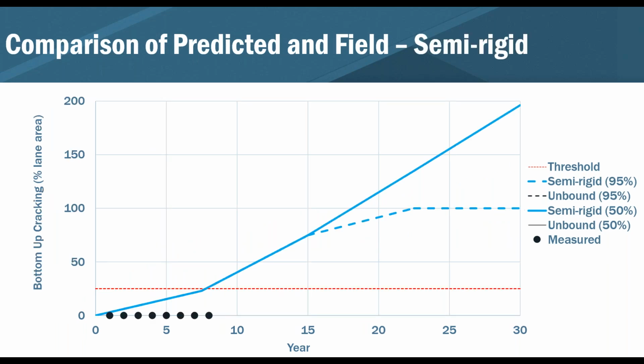Looking at the bottom up fatigue cracking, the difference here is on the semi-rigid case. This is considering both bottom up plus reflective, and so again, I think that's obviously what's driving the distress. At the end of the 30-year period, the predicted fatigue bottom up plus reflective cracking in the semi-rigid 50% reliability case is off the charts. It's 200%, which is always fun to have, but you can see it caps off at the 95% reliability. The program obviously caps it off at 100%, which makes a little bit more sense, I guess, mathematically than anything.